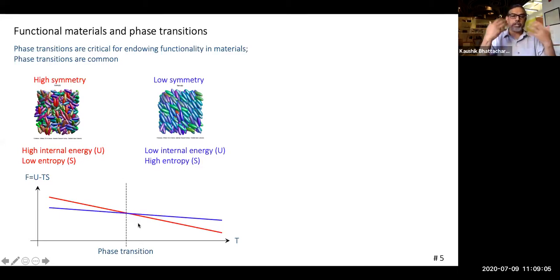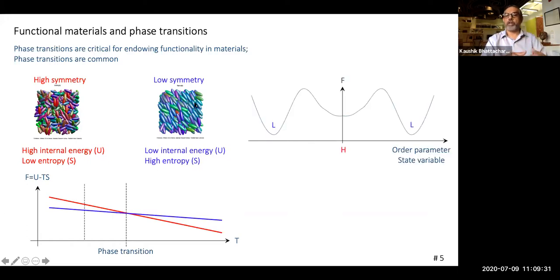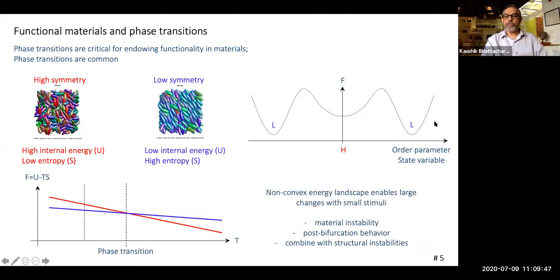Of course, this is a very simplified heuristic picture, but this is why you see lots and lots of phase transitions in nature in solid structures. What phase transitions also mean is that the energy landscape, which governs this, I've just plotted free energy as a function of temperature. I could also plot it as a function of a state variable or an order parameter which describes the state of the material. And if I did that, you find that the energy landscape is extremely non-convex, with a high symmetry phase being metastable at some temperature like this, and maybe multiple low symmetry phases with lower energy. So you have this extremely non-convex energy landscape.